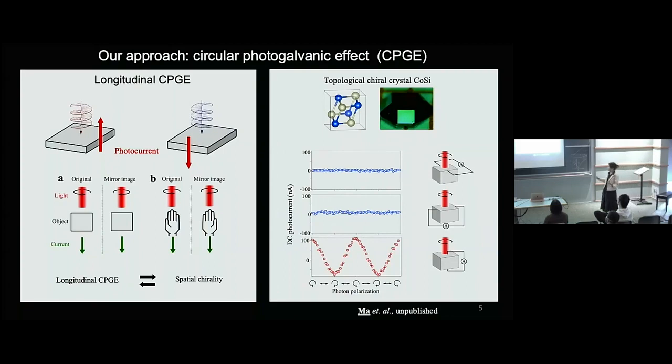It's a DC measurement. Okay, so for the first two cases, when we measure this transverse response, we do not see any modulation here, meaning, first, the circular light did not produce a current, and second, there is no difference between the left-handed and right-handed. But here in the longitudinal configurations, we see this huge modulation. Compared to other compounds, this is very huge modulation. And moreover, you see here, which corresponds to the left light, and here corresponds to the right light, there is a huge difference. And in the ideal case, there must be equal magnitude and opposite sign, which is here.